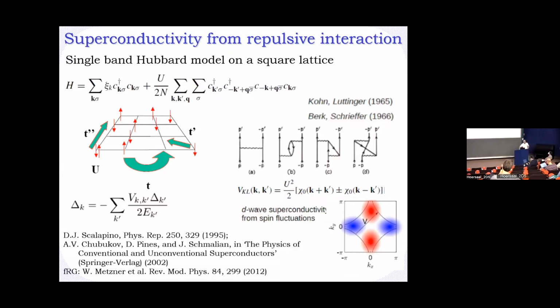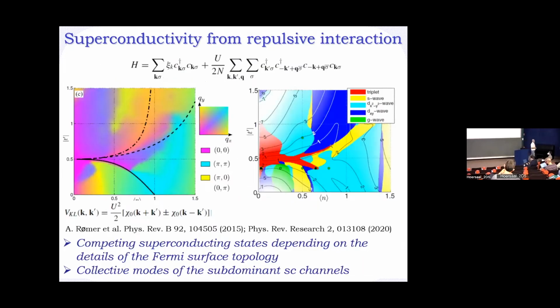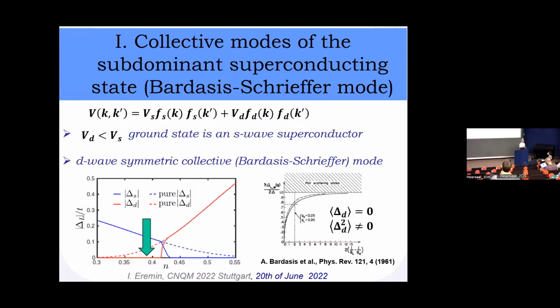But what you also know is that in principle, there is a whole zoo of pairing instabilities nearby, and if you just slightly change your filling, or change a little bit the details of the interaction, it actually turns out that you have a zoo of various instabilities. And even if the D wave is a dominant instability, the subdominant is always nearby and cannot be neglected as soon as you apply a perturbation, a nonlinear perturbation, which breaks inversion symmetry or diagonal symmetry of the lattice. So which is basically a starting point for me.